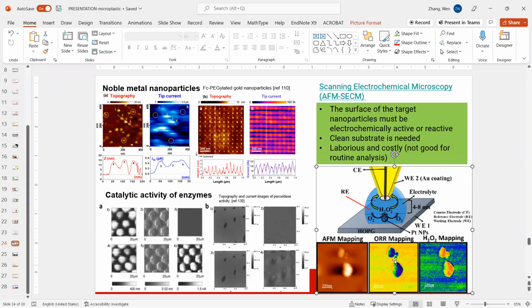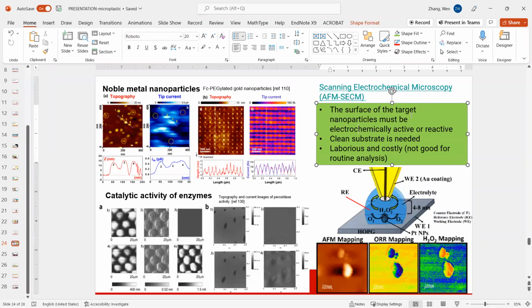You can sense where the reaction sites are located. And so by explaining such a principle, you probably realize that for plastic particles, this is a problem. So you have to make sure the plastic samples are electrically active or reactive. They must be somehow reactive towards the electrolytes, or otherwise you can still map them, but based on, let's say, the plastic particle interfering with the designed electrochemical reaction on your tip.